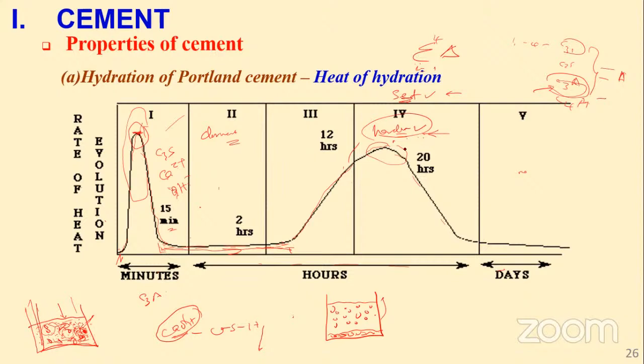Now, again, the fineness of cement. How does fineness have to do with the heat of hydration? You see, if you have very big lumps, of course this is for illustration purposes, and very fine particles of the same mass, the fine one has a higher surface area. The more you grind your particles, the higher the surface area for reaction to occur. And if you have a higher surface area, it means the reaction rate is high and the heat generated is high.